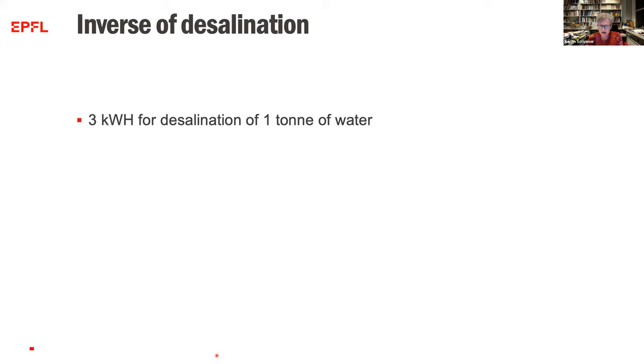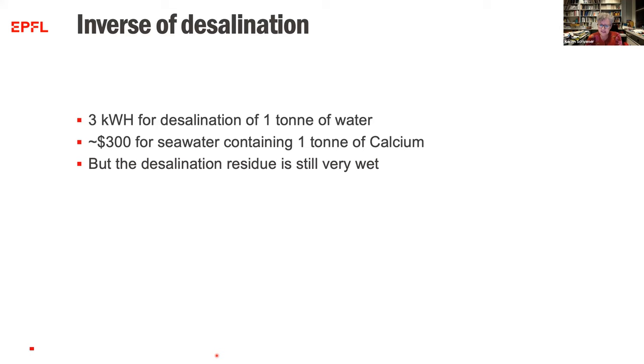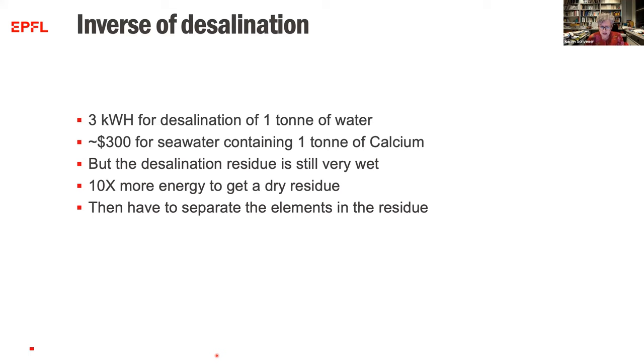And if you multiply that up to work out how much energy you need to extract potentially 1 ton of calcium, and what the cost of that energy is, it works out you would need about $300 for seawater containing 1 ton of calcium. Now, people could say, well, if you're doing desalination at any rate, that cost doesn't matter. But unfortunately, you don't end up with nice calcium after that, because the desalination residue is still very wet, and you would have to spend about 10 times that amount of energy to get a dry residue. And then you would have to separate the elements in the residue, which is the same as the situation of basalt, which I described earlier.